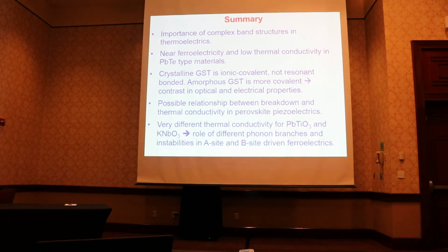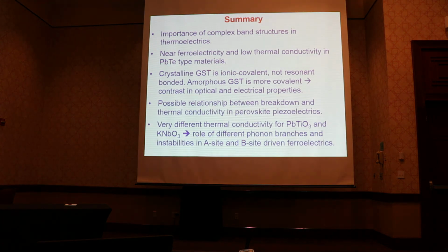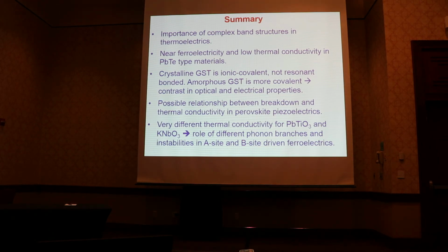So the importance of complex band structures in thermoelectrics, if you're interested in thermoelectrics. The nearness to ferroelectricity, which provides dielectric screening, which is important for mobility, and also is a mechanism for low thermal conductivity, which is also desirable in thermoelectrics. Some comments about GST, a little different than conventional wisdom, and then a relationship between lead-based, in other words, A-site-driven ferroelectricity and B-site-driven ferroelectricity, and thermal conductivity, which might be related to some problems with practical applications.